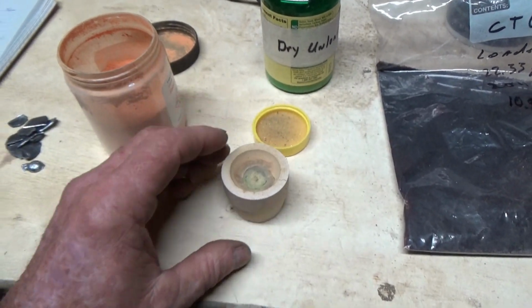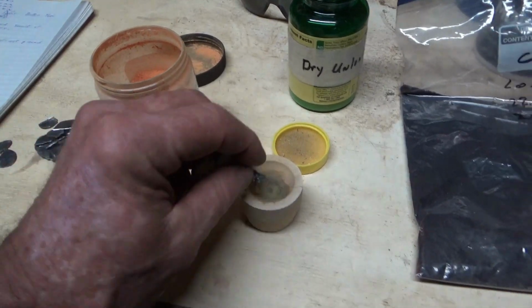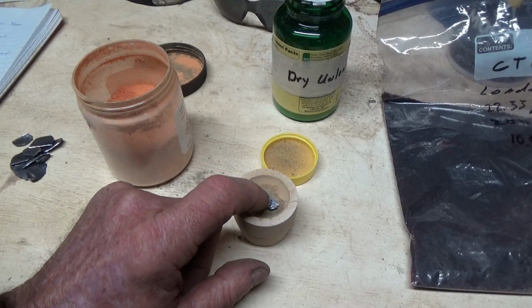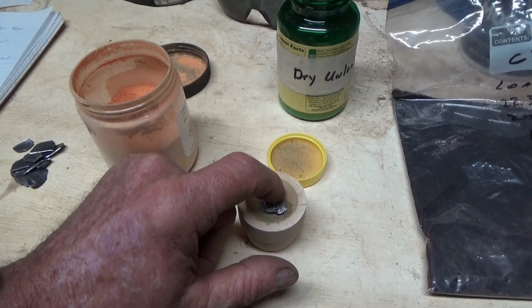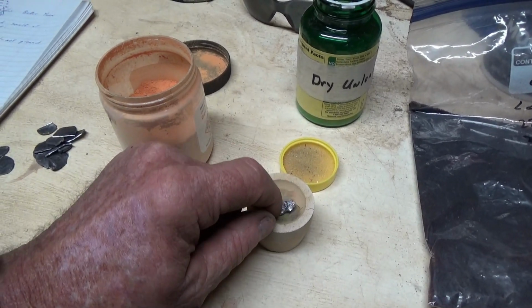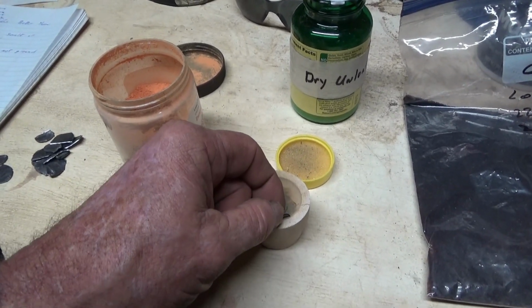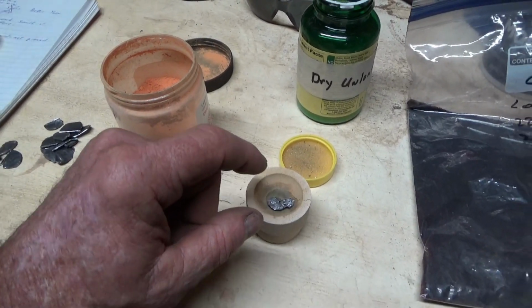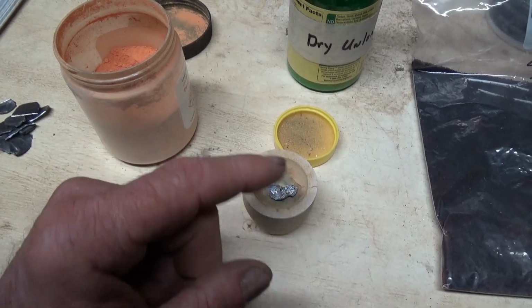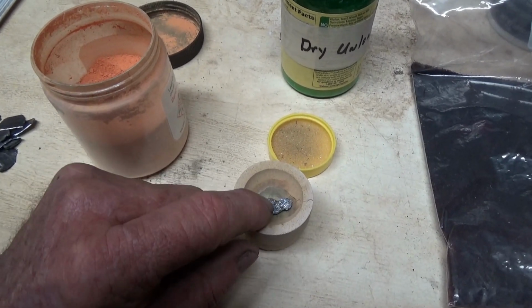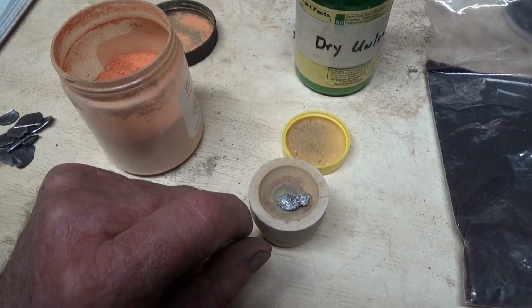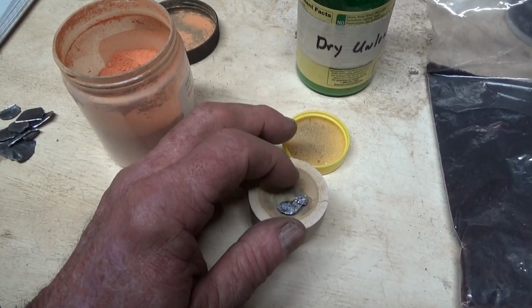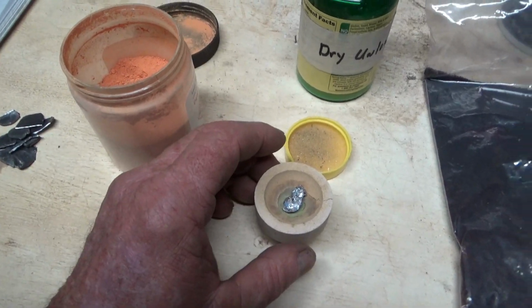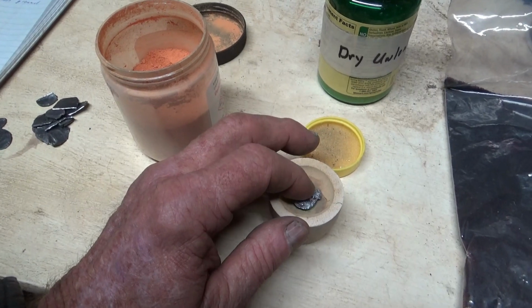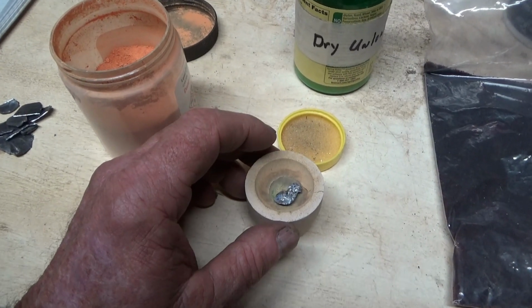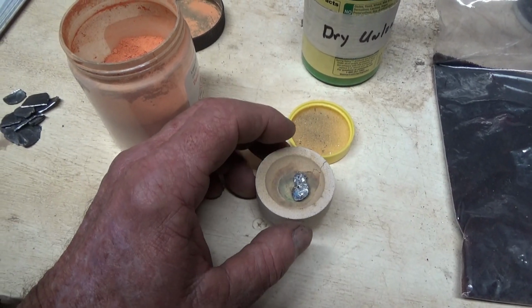And anyhow, as you heat this lead with oxygen, this will form lead oxide, which will soak into the cupel. The lead itself is not. The cupel repels liquid metals, but not liquid metal oxides. So as the metal oxides form and go into the cupel, this bead gets smaller and smaller and smaller until finally all that's left is the precious metals, because they don't oxidize, at least not very much. And then you wind up with a bead of gold and silver and maybe platinum group if you had any. And that is the cupellation.